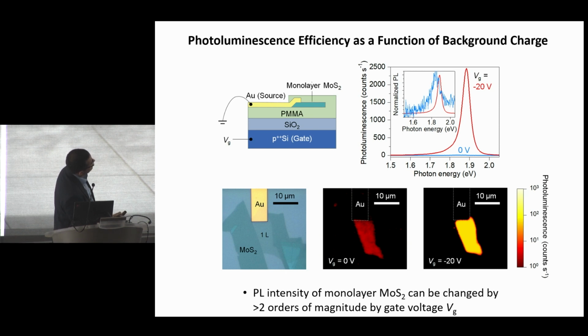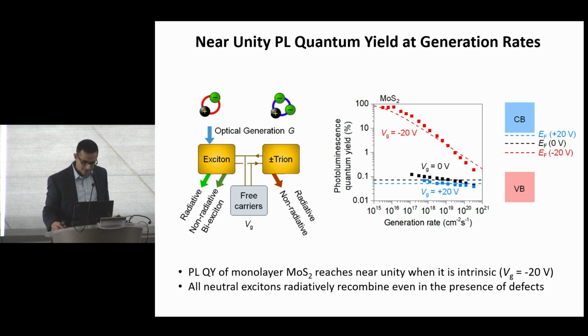When the gate voltage is 0, just like an as-made flake, this is for moly sulfide, the quantum yield is very, very low. The brightness is very low. You can see that the normalized spectrum is still there, but it's just very dim. When we apply a negative gate voltage, the material literally glows. It becomes very, very bright.